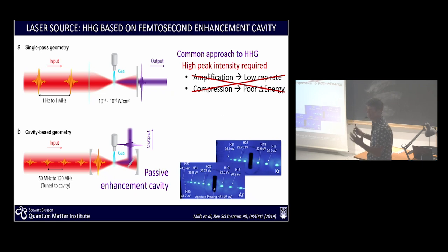The cavity is 5 meters long with many bounces, and so now we are all of a sudden in a very high repetition rate regime. What it means now also is we don't need to amplify, we don't need to compress the pulses, so very low peak powers, but many photons per second. Here you see some snapshots of the different harmonics you can get with different gases, argon or krypton, and so you can go all the way up to more than 40 electron volts this way.